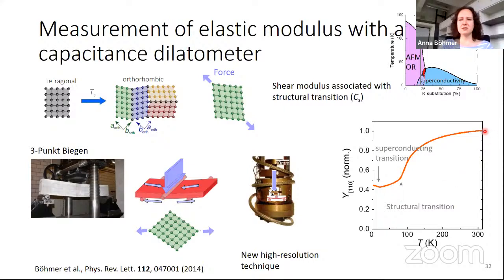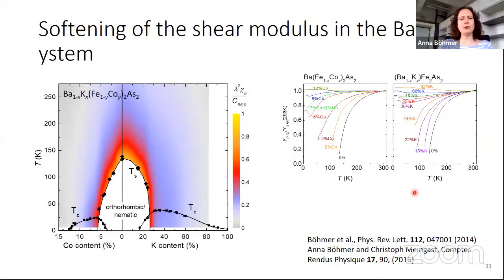Here are examples. When we go through our phase diagram, we see how much the sample bends more and more. There is our one transition, and then it bends a little bit less at the superconducting transition. So there's the competition again, this antagonistic behavior. We did that all over the phase diagram, so you can make fancy color plots out of this data, showing how much the material is soft. The quantity you can get from this is termed nematic susceptibility. Nematic was our distorted state, the strange orange one that we don't quite understand yet.